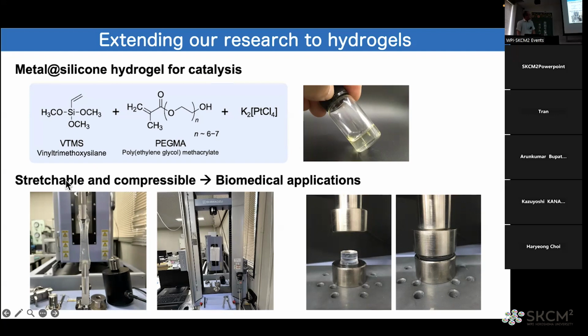Also, we are trying to prepare very flexible hydrogels, like stretchable and compressible hydrogels. Like in this picture here, you can see the hydrogel before stretching, and after stretching. It's difficult to see this here. Okay, like more than 1,000% stretching strains. And also this is compressible, so very flexible. And now we are thinking of applications to biomedical purposes. And we are still trying to improve the bioactivity and improve the mechanical properties by designing the cross-linking structure in the network. And also, we have to put some bioactive species in the gel we are trying now.